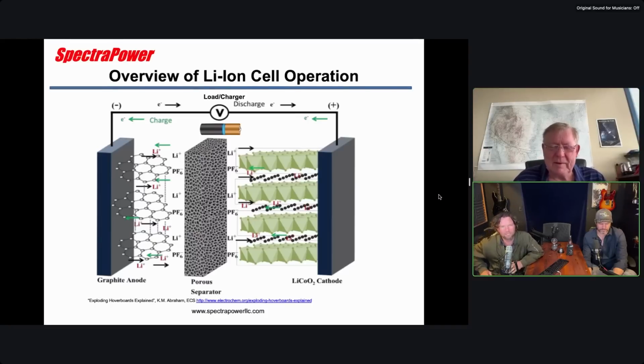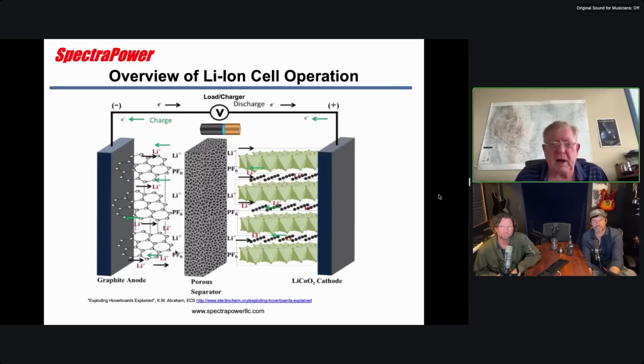When you have these explosions, a lot of it's due to the liquid getting it started. What you typically get is what's called a dendrite, and it'll puncture this separator. This separator is just a very thin sheet of plastic. Sometimes they'll put a coating of ceramic on the top to try and make it stronger, which helps, but isn't a perfect solution. So one of the things we talked about is getting lithium metal forming on the surface of, say, your anode during an overcharge or other situation, or a cold charge. That lithium, when it plates, if you then cycle the cell, you're moving the lithium back and forth. Lithium doesn't form plated metal very well. You have to carefully control that process.